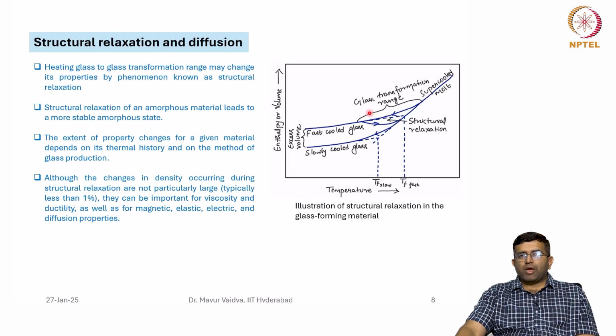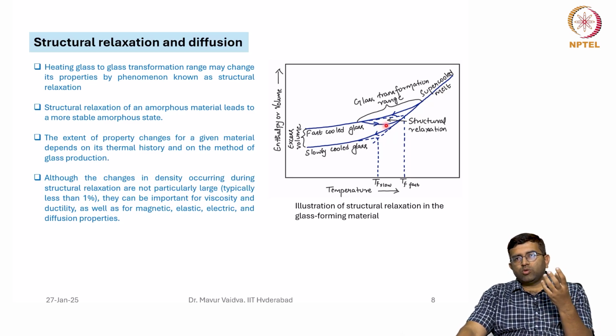So, this is how it is schematically represented. Suppose this is the glass transformation range, and now, for example, if you heat a fast cooled glass to a temperature above this glass transition temperature, you will see that the excess volume that it had starts to anneal out, and the volume starts to decrease. So it has still not reached crystallization. Crystallization has not occurred, but the excess volume has started to come down. This phenomenon is known as structural relaxation.